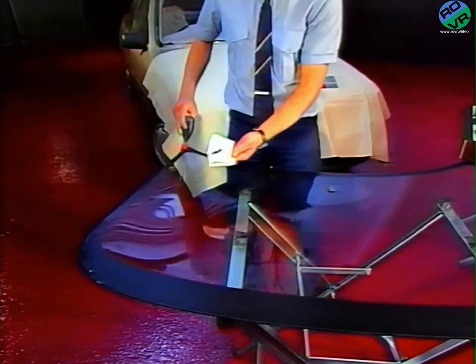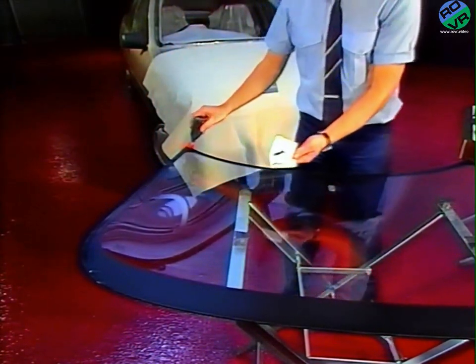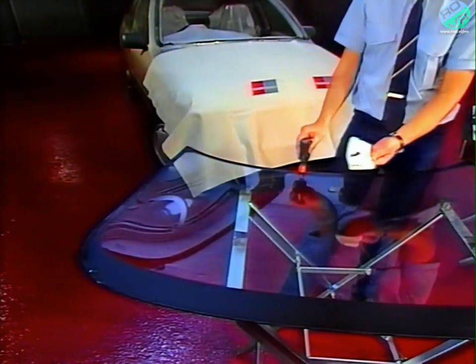Incidentally, it's coloured black to protect the urethane from sunlight, as ultraviolet rays can destroy the bond. This is an important point and indicates the necessity for a black primer. As you can see, the obscuration band on the glass is not totally black and the primer is much denser. This ensures that ultraviolet rays do not affect the adhesive bond.